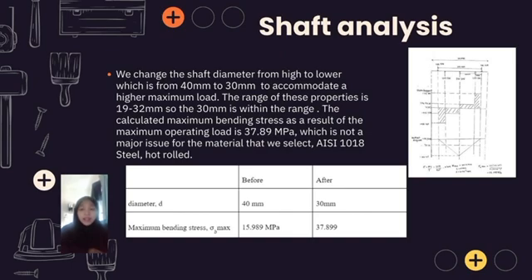The calculated maximum bending stress as a result of the maximum operating load is 37.89 megapascal, which is not a major issue for the material that we selected. The material is AISI 1018 steel hot rolled. At the bottom, we make a comparison before and after for the diameter. Before, the diameter is 40 mm and after is 30 mm. For the before, the maximum bending stress is 15.89 megapascal, and for the after it is 37.899 megapascal. From this maximum bending stress, we get the maximum load at diameter 30 mm.